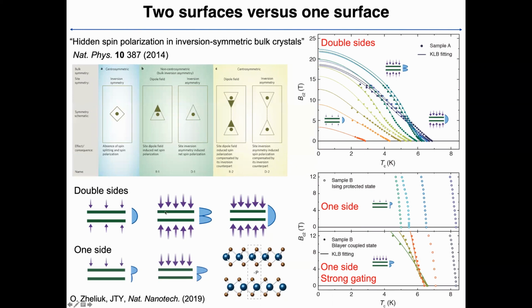If you increase the gate, the layers start to be separated. The system start to behave like an individual layer. If we keep gating, the layer again gets coupled because electric field gets penetrated, and again this system become a coupled system. So this is what we can see. So from the weak gating, we have very low upper critical field, indicating the system is coupled. If we increase the gating, we start to see the increase of upper critical field. If the gating is even higher with higher TC, again the upper critical field start to get lowered because the system gets coupled to each other.